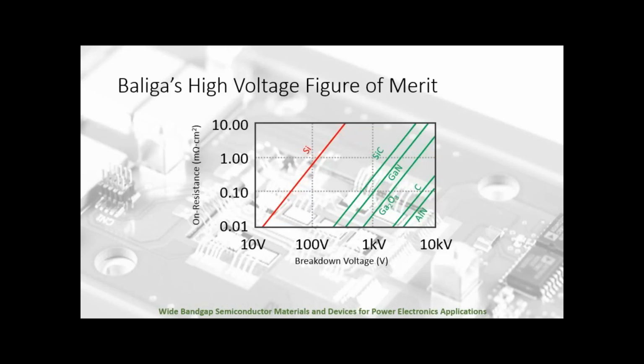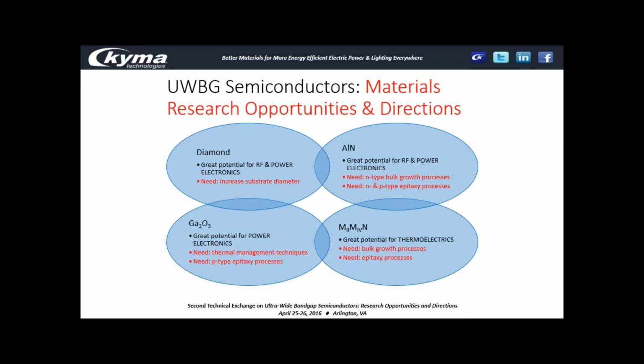And so you can see very clearly that silicon carbide's way better than silicon for a given blocking voltage to get a low on resistance. GaN's quite a bit bigger, and it's a log scale, right? So GaN's quite a bit better. Gallium oxide looks tantalizing, but the previous slide shows it's got low thermal conductivity. One has to think about that. And then the C there is for diamond, and then even aluminum nitride's even further out. So these things are hugely of interest to many folk.